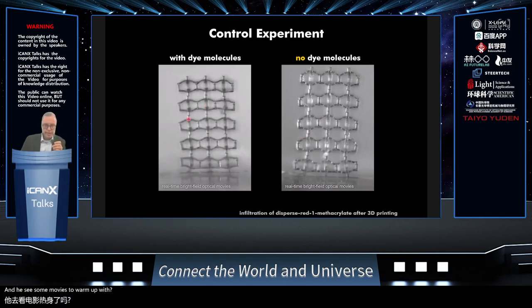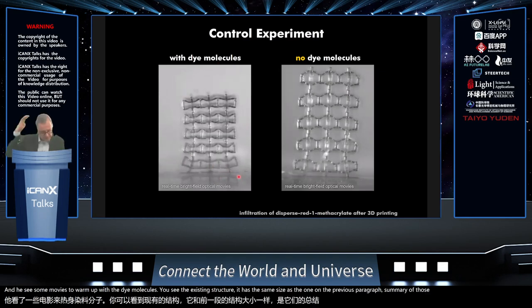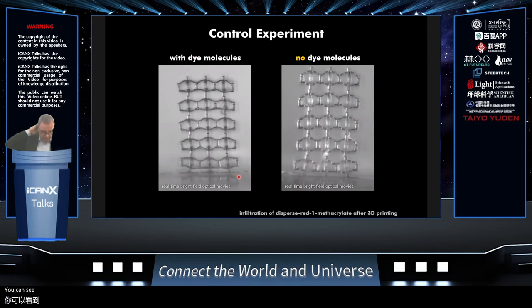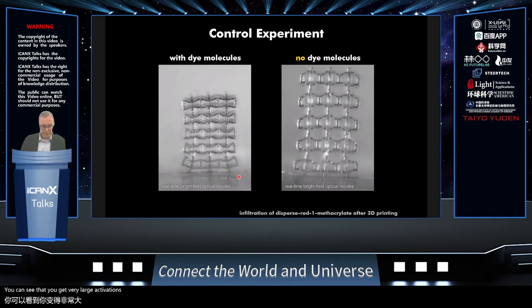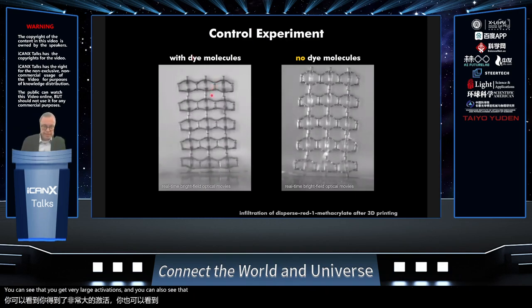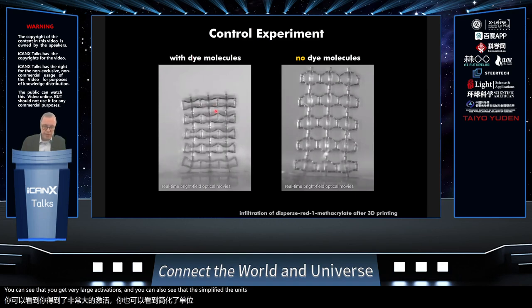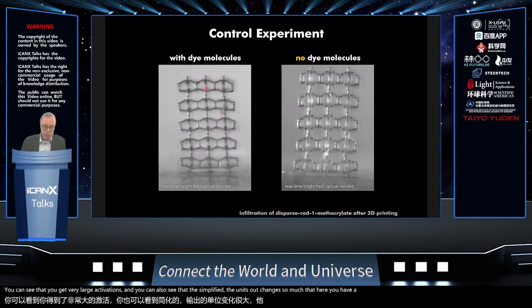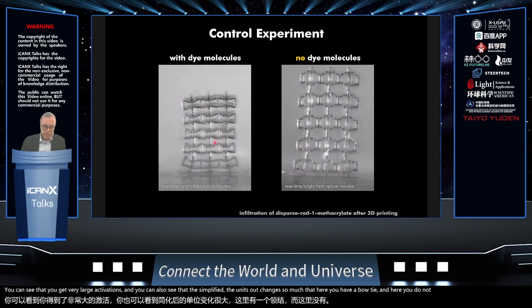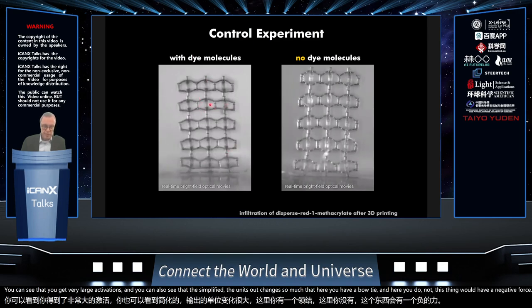With the dye molecules, you see the auxetic structure. It has the same size as the one on the previous view graph. Sorry that there is no scale bar here. You can see that you get very large actuations. And you can also see that the unit cell changes so much that here you have a bow tie and here you do not. So this thing will have a negative Poisson's ratio. This thing has a positive Poisson's ratio.